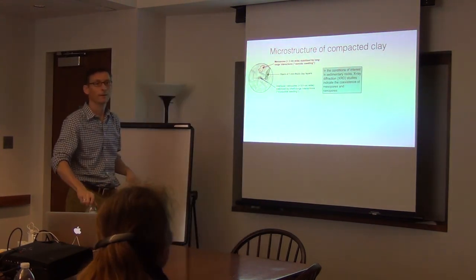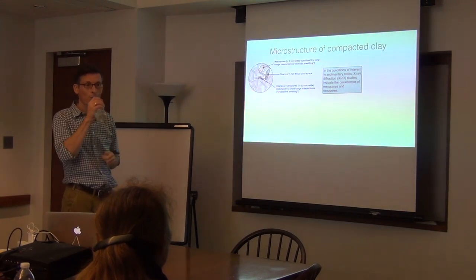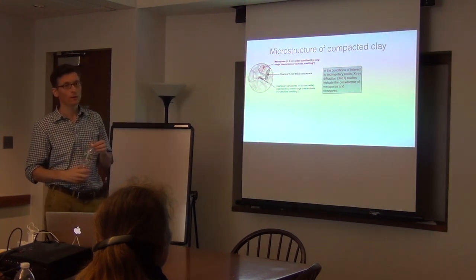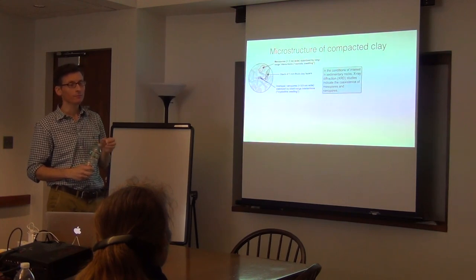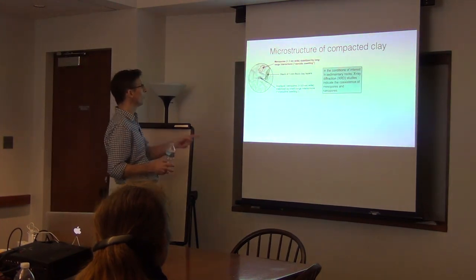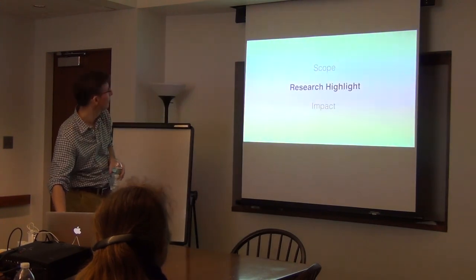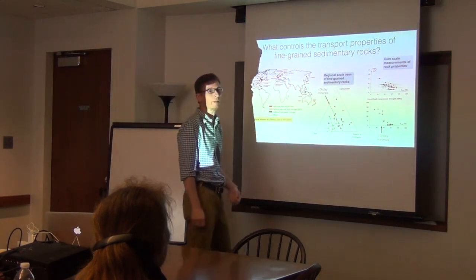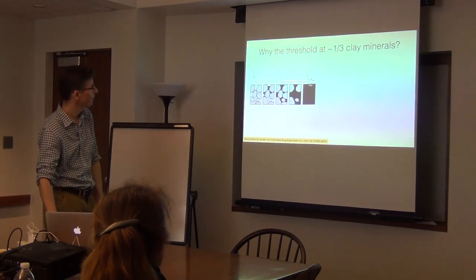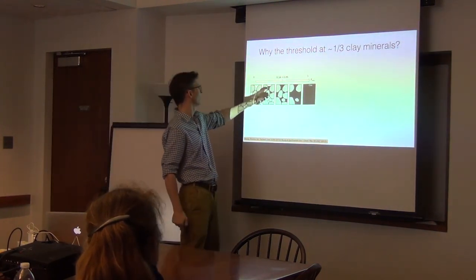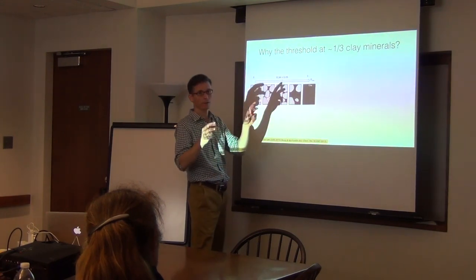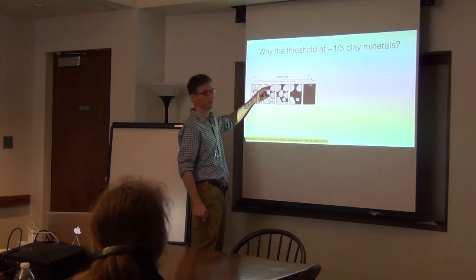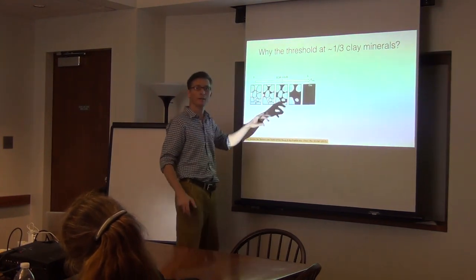Throughout, I'm just talking about clay minerals — all clay minerals by mass determined by X-ray diffraction. There's not good data on the microstructure, but people have been trying to guess it based on X-ray diffraction data and circumstantial evidence from anion exclusion from the pore space. What they typically find is that there are two types of pores: stacks of parallel clay particles with nanopores between them of less than 0.9 nanometers, and larger pores wider than 3 nanometers, with a pore width range between 0.9 and 3 nanometers that seems to be not allowed.